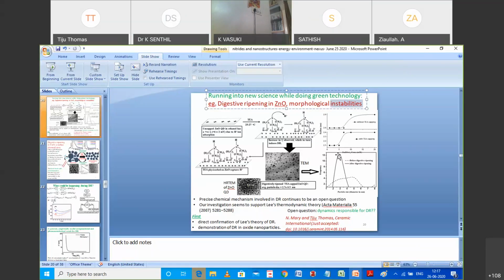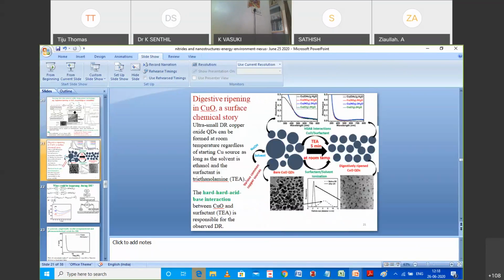Why would this be important? Because in the quantum mechanical regime, it turns out that size matters. If the size is exactly the same, all of them would have exactly the same electronic structure. So size matters, and this has been an activity that has been going on for a while in the group. And we have now come to develop a few stories, not just with zinc oxide, but with other oxides as well. Potentially, it can be extended to other materials as well by using a hard acid-base interaction approach to choosing surfactants that allow for particle sizes to go from what looks like this to what looks like this. And as a consequence, ensuring that the particle size distribution goes to near zero.